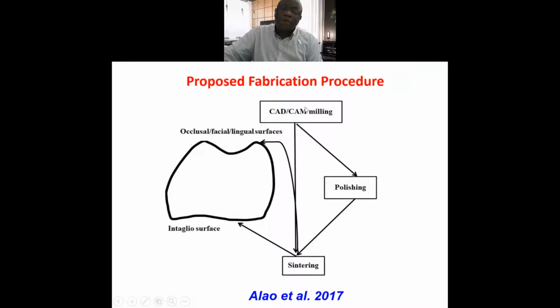So once it is CAD-CAM milled, then it needs to be polished. Okay, then after polishing, then sintering. This one will lead to a smooth surface. However, the intaglio surface needs to be roughened. So CAD-CAM milling followed by sintering will roughen the surface for easy adhesion with dentine or substrate.